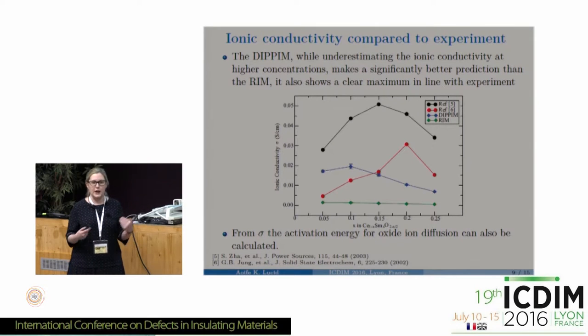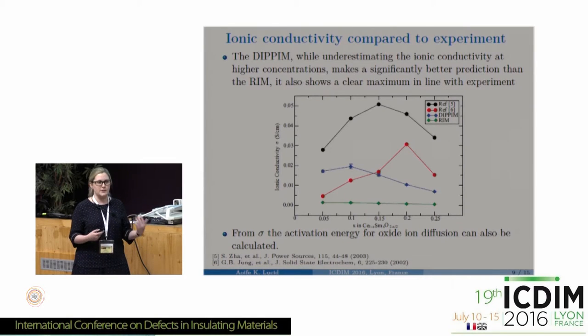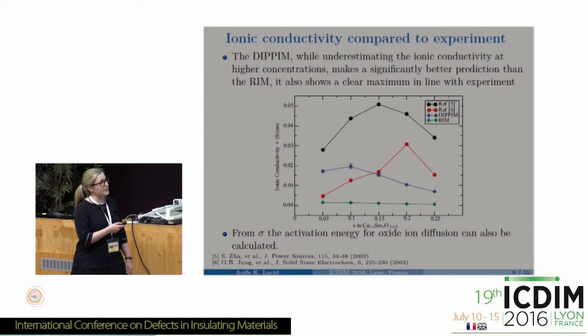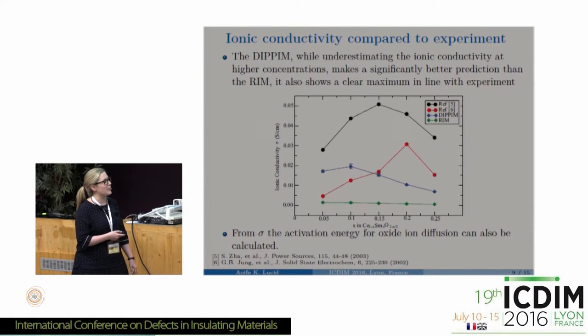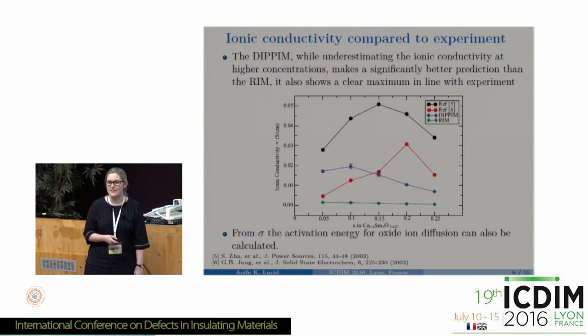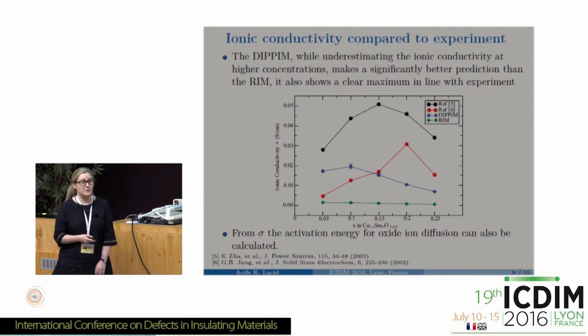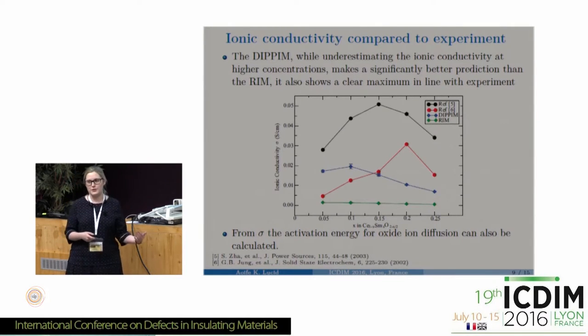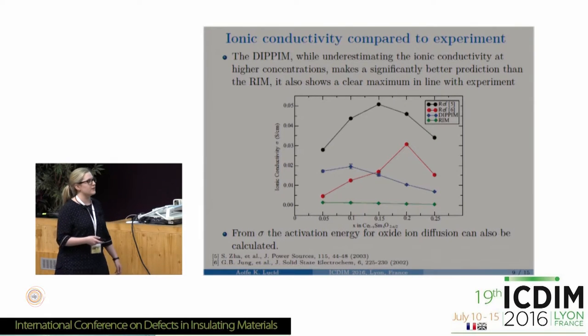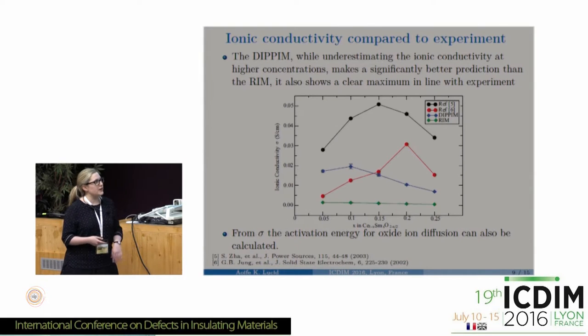The dipole polarisable model shows at least a clear maximum in conductivity, which is a good start, and falls within the variation seen in experiment. The rigid ion model is effectively a flat line when compared to experimental values, further confirming that it would not be sufficient for modelling ionic conductivities in these materials due to the highly polarisable nature of the O²⁻ ions. Oxide ion diffusion activation energies can also be calculated from these simulations.